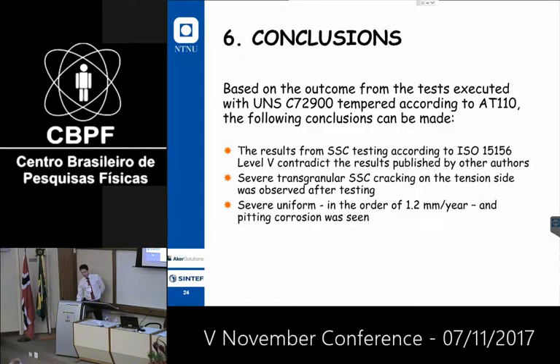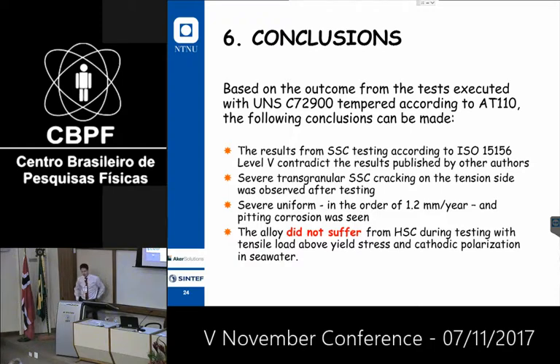And this makes us conclude that this copper-based material is not suitable for that high amount of H2S according to level 5, contradicting some literature and the data card, because we have severe transgranular cracking on the tension side and severe uniform plus pitting corrosion. However, the sample did not suffer from hydrogen-induced stress cracking.